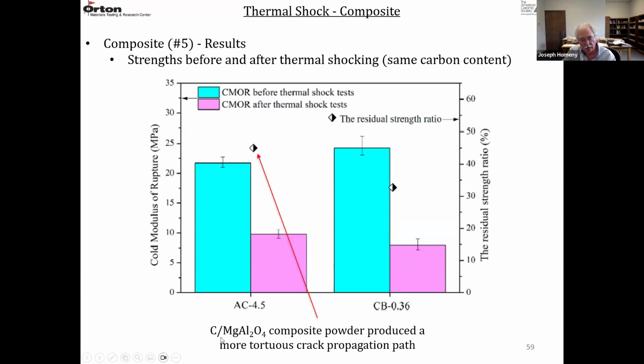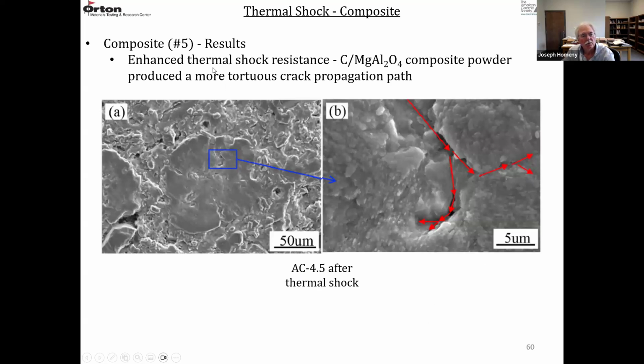So when you added these composite powders, they produced a more tortuous crack path. So even though these carbon contents are exactly the same, the nanographene carbon incorporated in the spinel created a more tortuous crack path and improved the thermal shock resistance slightly over this one with just the carbon black. So they're saying there was enhanced thermal shock resistance with the composite powder additions, producing more tortuous crack paths.